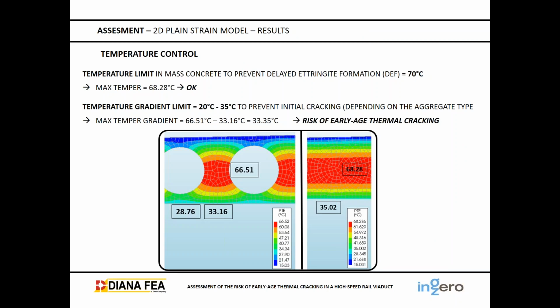make some assessments, after seeing those images, some results or conclusions. Related to the temperature control, the temperature limit in the mass concrete to prevent delayed ettringite formation is 70 degrees. So we have a max temperature of 68 degrees, so we are nearly, but in a safe place. Regarding the temperature gradient limit, which is recommended to be between 20 degrees and 35 degrees to prevent initial cracking, it depends on the aggregate type, okay? Here we have a maximum temperature gradient of 35. So we are at the upper limit. So there is, in fact, a risk of early age thermal cracking.